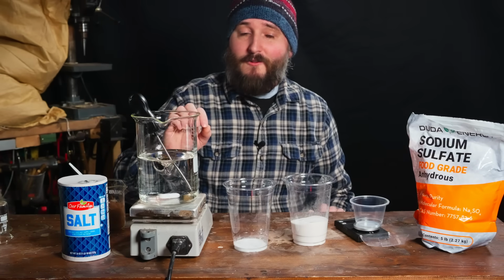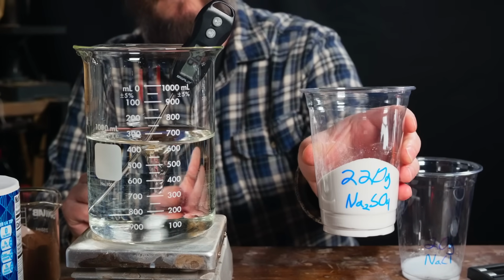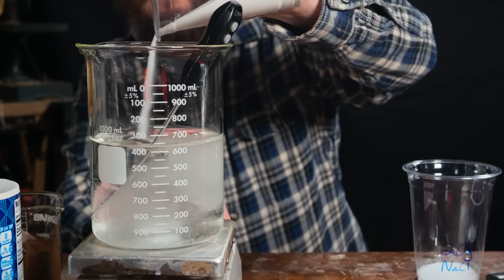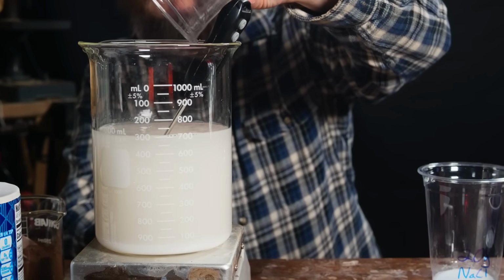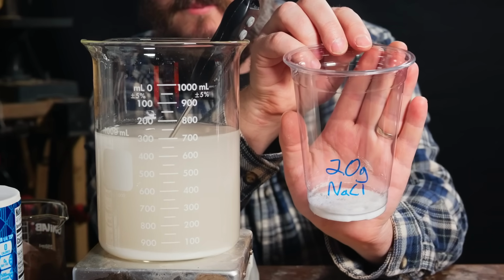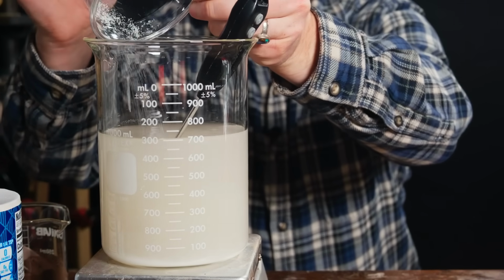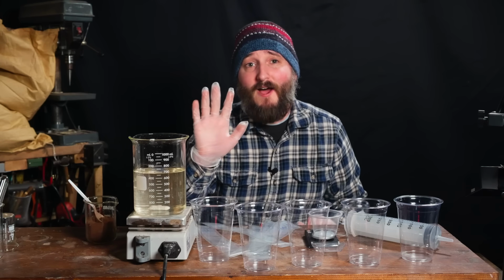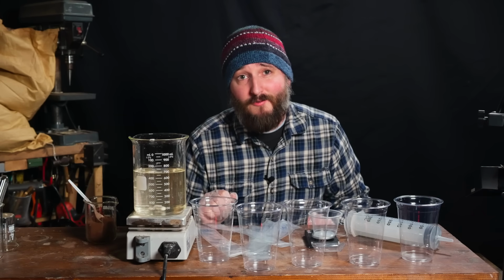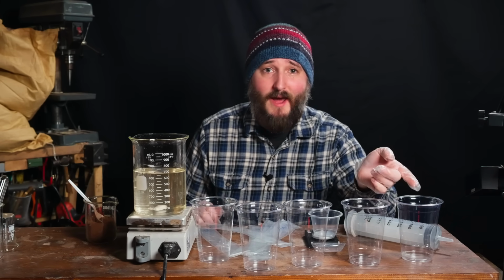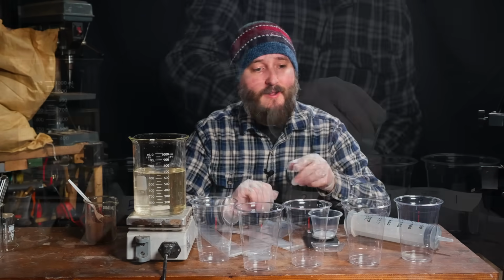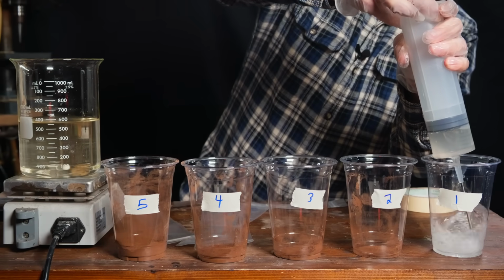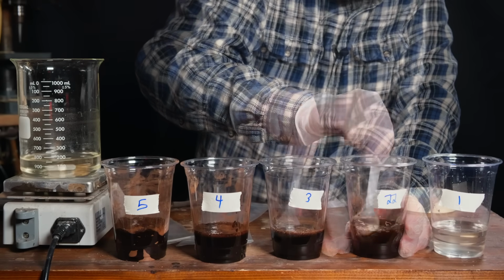This will be a fairly large quantity, which I will divide into multiple samples after mixing so that we have consistency between our tests. From this finished PCM solution, I'll extract 5 100 milliliter samples. The first will have no additives as a control, and then I'll add 1, 5, 10, and 20 grams of lignosulfonate. The test will be to see if any of these reduce or hopefully prevent crystal sedimentation altogether.